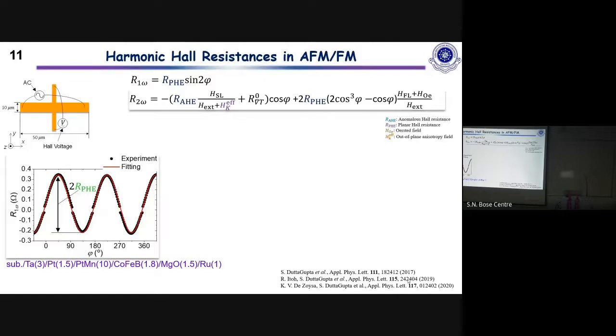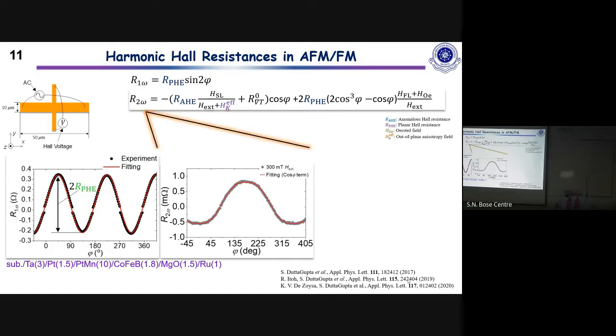This is the first harmonic resistance as a function of the magnetic field which is rotated in the plane. This phi is the angle between this x direction, which is the direction of current, and the magnetic field. So this follows this kind of behavior, which roughly follows the sine. And this is how the second harmonic looks as a function of phi.